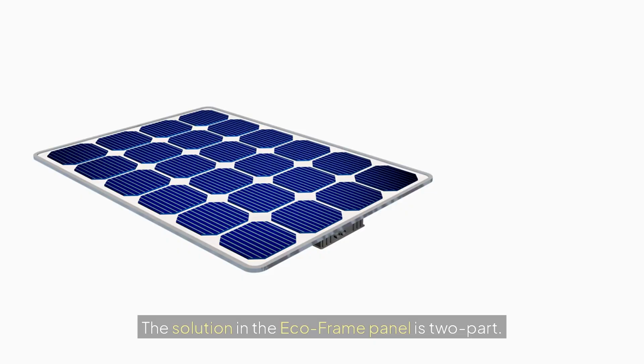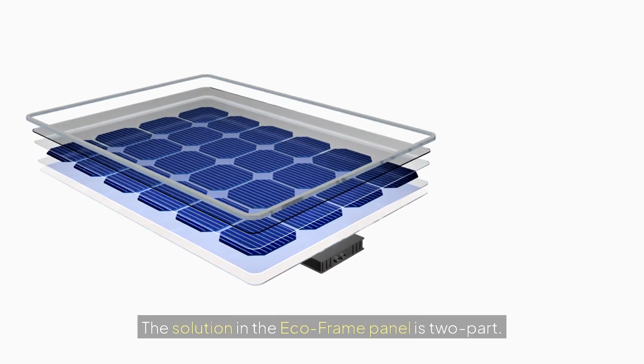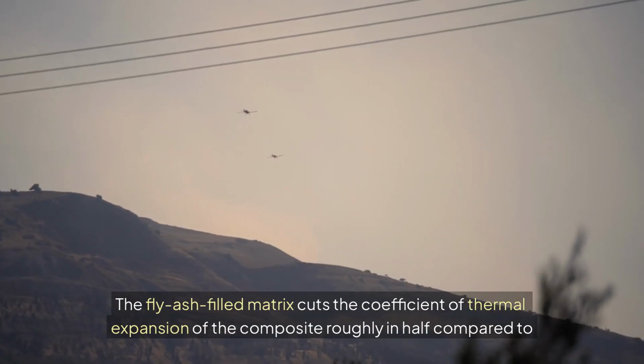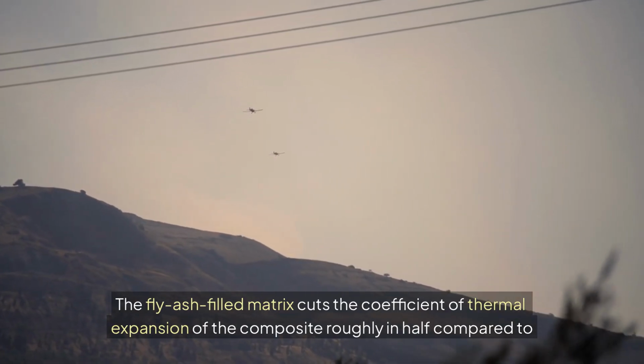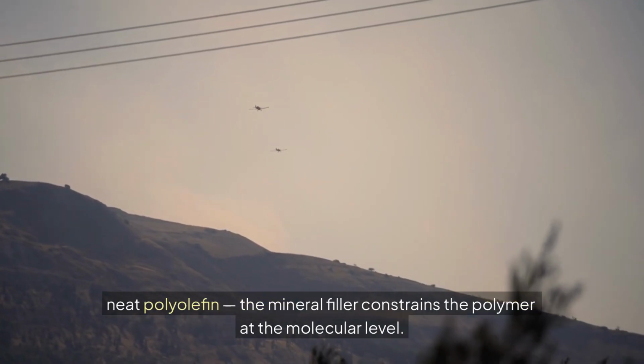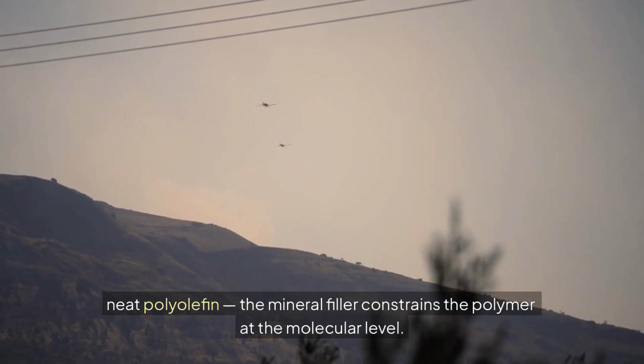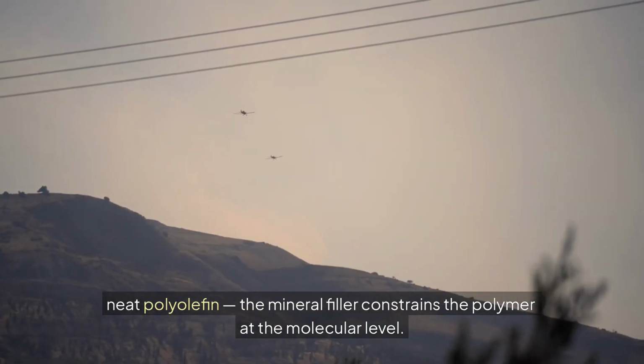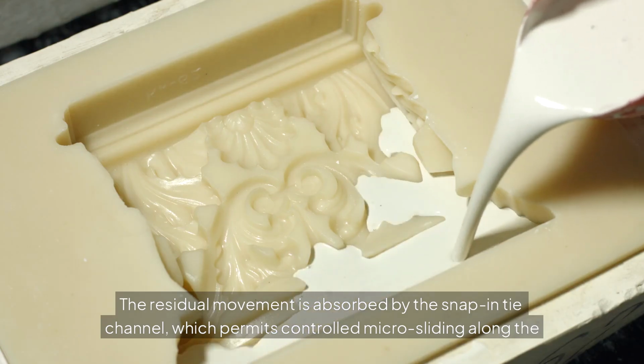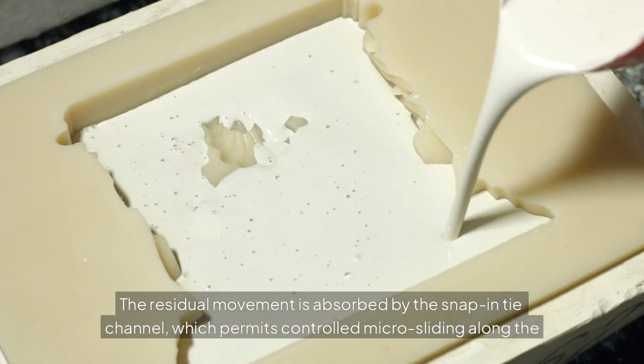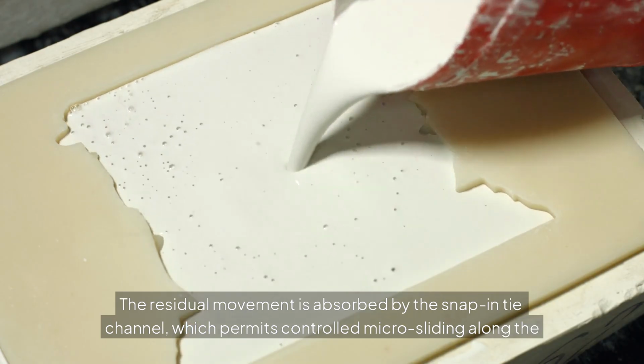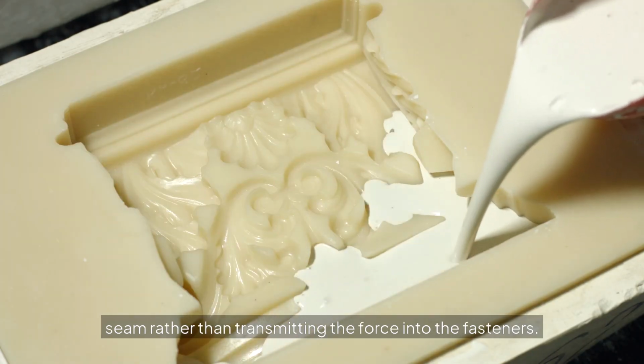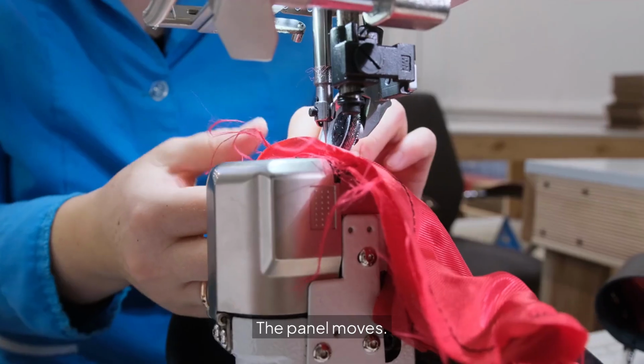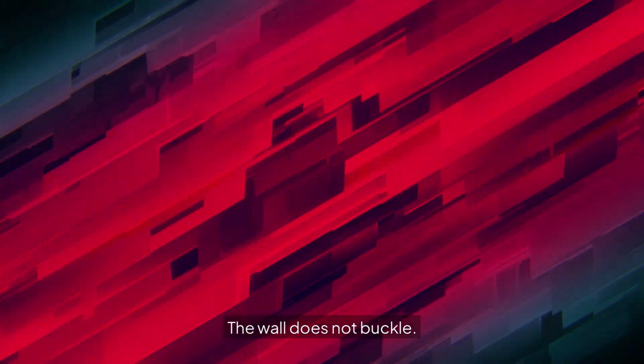The solution in the EcoFrame panel is 2-part. The fly ash-filled matrix cuts the coefficient of thermal expansion of the composite roughly in half compared to neat polyolefin. The mineral filler constrains the polymer at the molecular level. The residual movement is absorbed by the snap-in tie channel, which permits controlled microsliding along the seam rather than transmitting the force into the fasteners. The panel moves. The wall does not buckle.